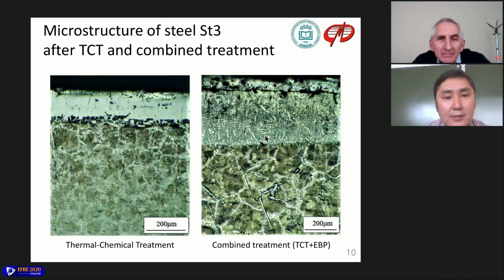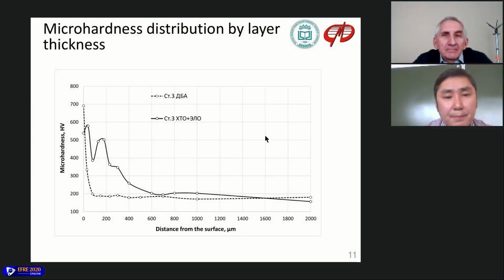So this is the result of combined treatment microstructure, and microhardness distribution showed us that maximum microhardness after TCT is around 700 HV. On the graph, it is marked as in the. After that, values drastically drop to around 200. On the contrary, in the microhardness distribution of combined treatment, which is like HTO plus LO, we can see vibrations in the values. Vibrations from 550 to 350 HV, and then values gradually drop to around 200 HV.